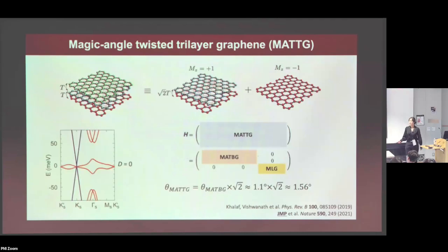When you calculate the band structure for this system, this is what you get. You have this orange band from the magic angle twisted bilayer graphene-like block, exactly what we expected, similar to what we already saw with the flat bands and the remote bands. But coexisting is a pristine monolayer graphene-like Dirac band happening at the same time. That's how you can picture this system.